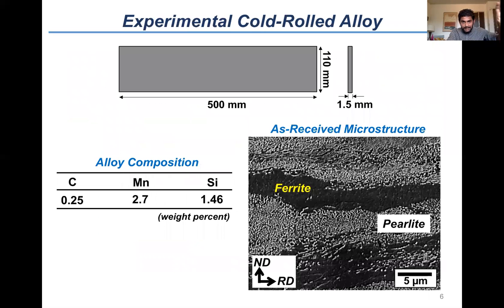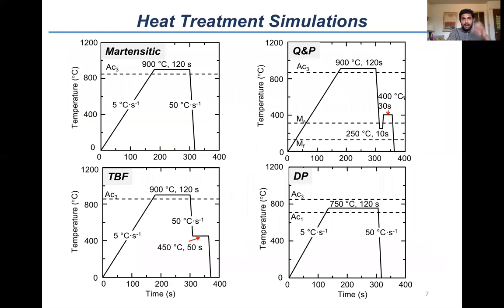We started with an experimental cold rolled alloy having an AHSS composition. The as-received microstructure was cold rolled ferrite-pearlite. We developed 4 different heat treatment cycles to develop 4 different microstructures. This is the martensitic cycle, the quench and partition, or the Q&P cycle, the TRIP bainitic ferrite, or the TBF cycle, and here is the dual phase cycle, or the DP cycle.